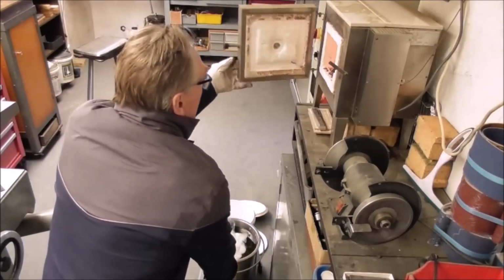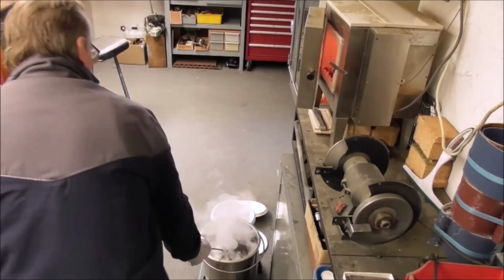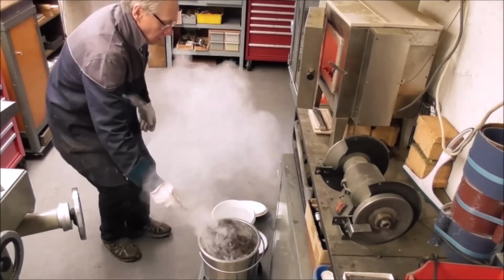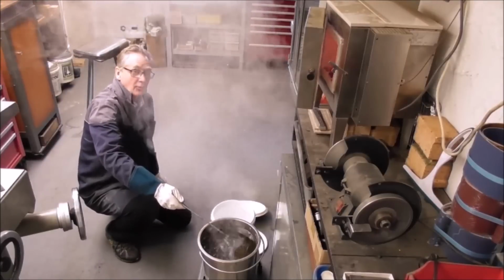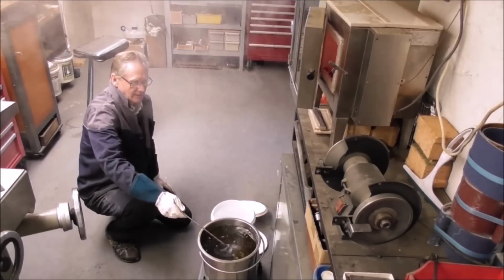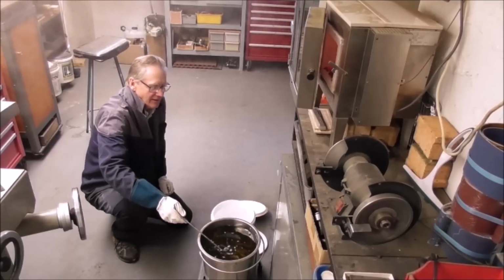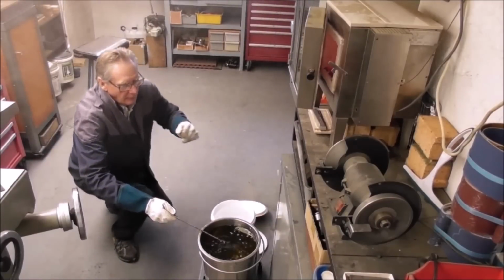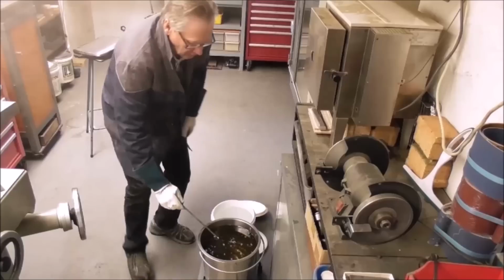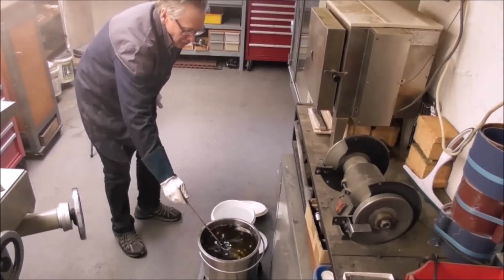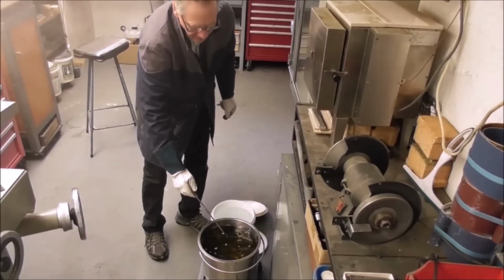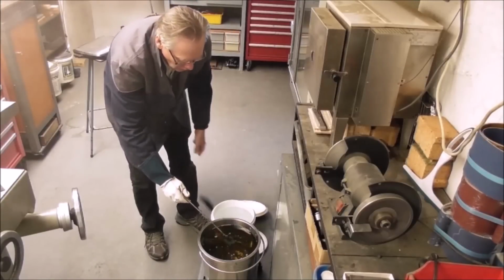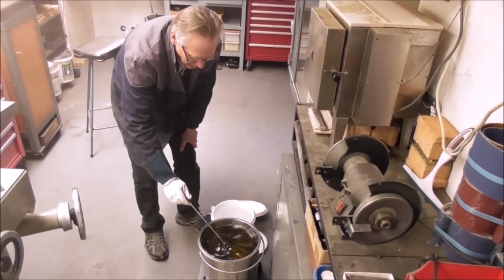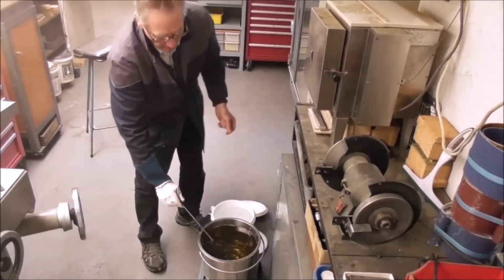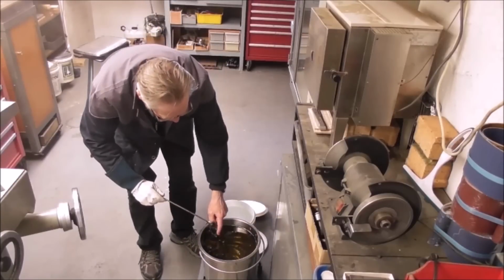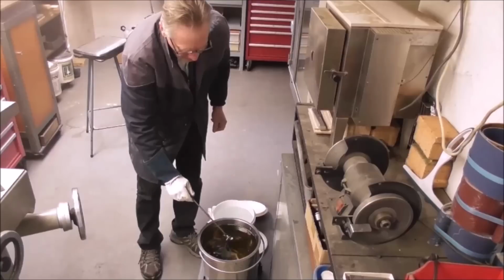Into the oil. Close the door, move it around, get out of the way of the camera, don't breathe the smoke. Smells like a third world fish and chip shop here at the moment. Okay, so we're going to leave it in there until it's, going to close that door on the other parts or they'll go cold. So they've been at 800 degrees C for about half an hour. Now I need to get this down to at least 150 degrees C so that it doesn't temper with its own residual heat. Yelch, it's still a couple of hundred degrees C.